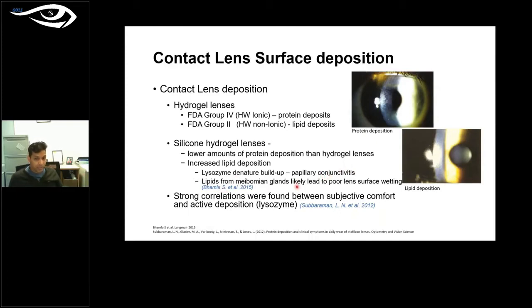Lipids from meibomian glands are also likely to lead to poor surface wetting as well. So it's not just the lysozyme from the tears, but also lipids coming from meibomian glands have been shown to deposit on the lens surface. So again, hydrogel lenses and silicone hydrogel lenses both deposit. And why we are discussing deposition in relation to comfort is because there are strong correlations found between subjective comfort and active deposition of lysozyme. And of course, I mentioned that in the rest of the talk I'll be focusing more on silicone hydrogel lenses than hydrogel lenses. So that's why I'll be talking more about lysozyme than normal protein deposition that can occur in other types of contact lenses.